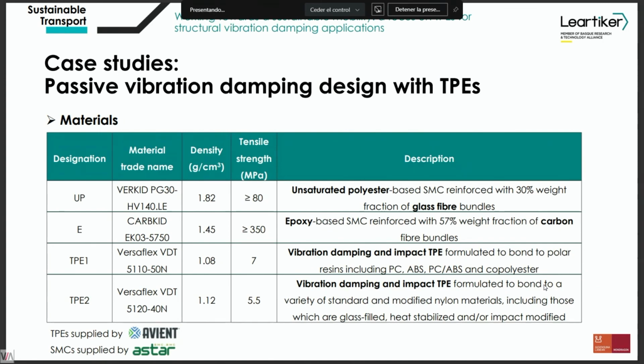In terms of material selection, the TPEs that we used for this study were supplied by Avient, because Avient has some special grades of TPE materials with very good vibration damping capability at room temperature, and they are also formulated to bond with different kinds of materials. In our case, we were interested in blending with a polyester-based SMC reinforced with glass fiber, and an epoxy-based SMC reinforced with carbon fiber. That's why we selected these two Avient TPEs with good vibration damping capability, as we will see later, tan delta higher than 0.3, and good bonding capability with these two specific SMCs.